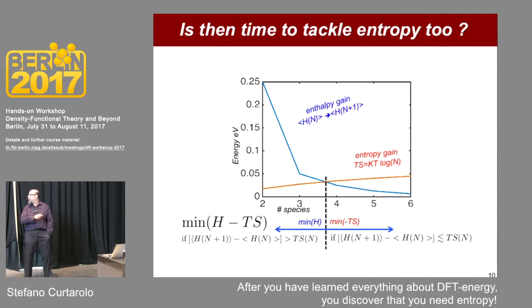So you say, there is a trick here. The red one is monotonically increasing. The blue one is monotonically decreasing. Eventually, they will have a threshold. It's unclear to me where exactly this threshold is, because remember, this is based on some assumptions and some coarse data. But thanks to NOMAD, we're going to have a much better blue line in 5 years, and we're going to discover that instead of being 3.8, it's 3.9, whatever. But the idea is that you will eventually have a threshold.